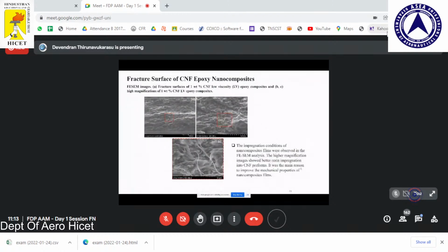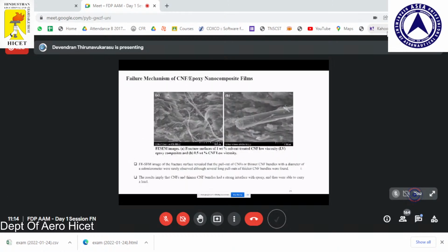This is the fracture surface of our composite film. We wanted to find out how the epoxy resin impregnates it. So we did the fracture test, and we can clearly observe the fiber and the resin bonding, and we get a good impregnation property. We confirmed that our composite films have better impregnation using FESEM analysis. The fiber fracture revealed pullout of nanofibers or thin fiber bundles with sub-micrometer diameters, rarely observed in the FESEM analysis. Finally, we get clarity on it.